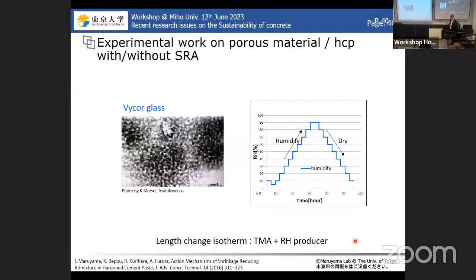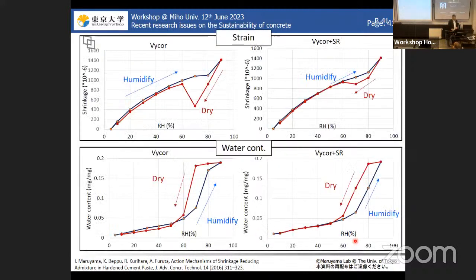So from a poromechanics point of view, we try to evaluate the role of the shrinkage reducing agent by using Vycor glass. We change the relative humidity, something like this, and measure the mass change and the shrinkage. And also, we try to put the SRA molecule inside of the Vycor glass, and how the behavior is changed was confirmed. And these are the experimental results.